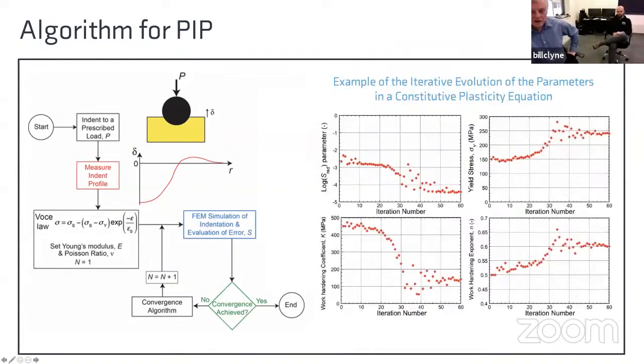So here's the kind of thing that goes on during that process. This is actually showing you how that misfit parameter, that S value, is changing with repeated iterations. This is a log scale, so down here we're down to very low values, and we're aiming to get a value somewhere around here, 10 to the minus 4 or so. So these are the corresponding values of the plasticity parameters being iteratively changed until eventually we settle down to something which is the best fit. And all that happens rather quickly during an automated process.